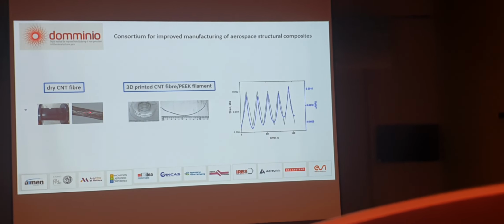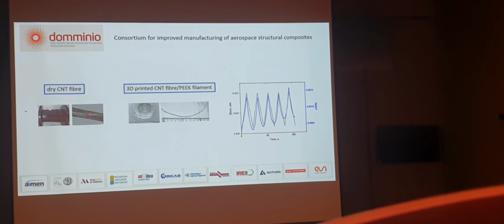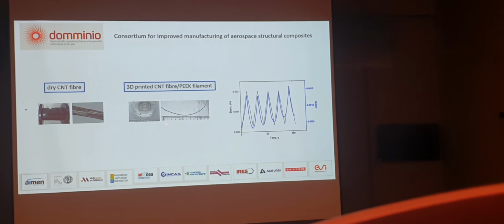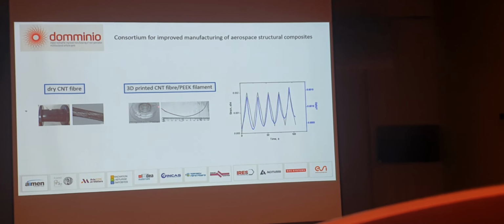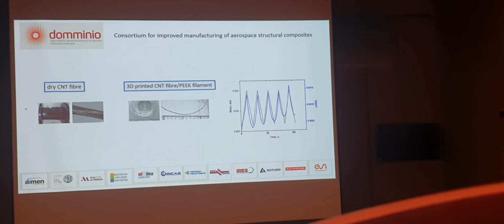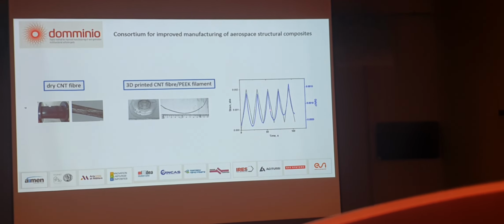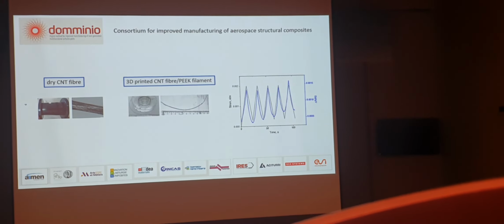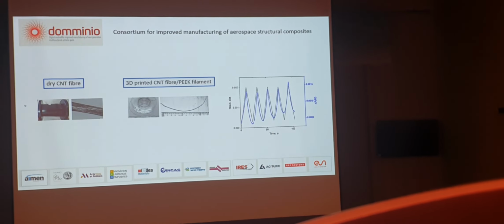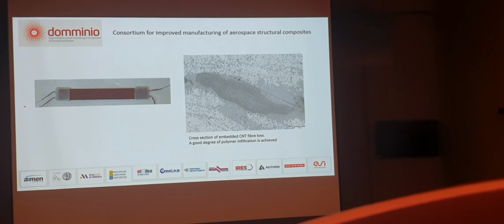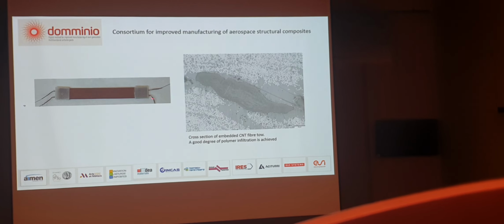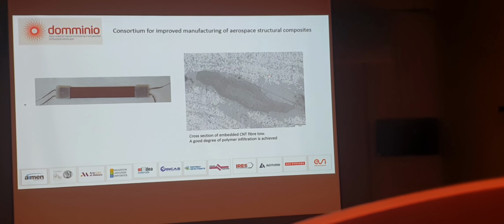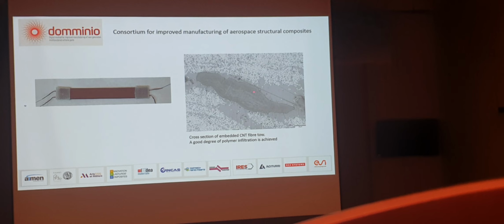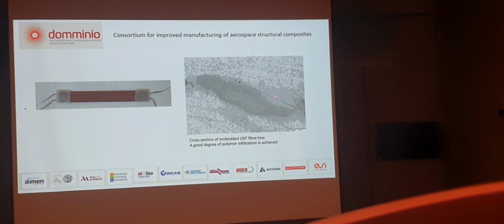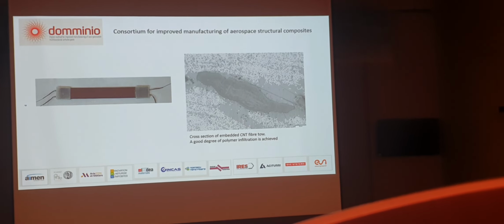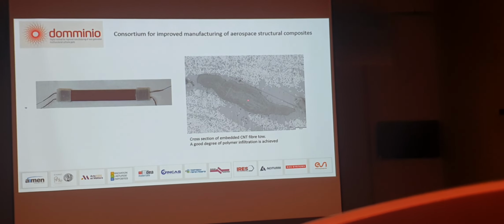So for instance, we take tows or thick fibers from commercial vendors. We're part of a big consortium, and we have some colleagues in Galicia that are 3D printing a filament of CNT tows with PEEK, and they can make sort of 50 meters or so. We are looking at the piezo-resistance because it increases slightly when you put the polymer phase inside. And of course, PEEK is chosen because it is the polymer for aerospace. Then we produce composite panels and cut off some small coupons. This is a composite panel with fully embedded contacts, and you can see here a cross section. These are carbon fibers, aerospace carbon fibers, and you can see here this film. Of course, there's a resin-rich area here, which is not too bad because it prevents any shorting between the two. And we seem to have very good infiltration of PEEK into these CNT fibers.